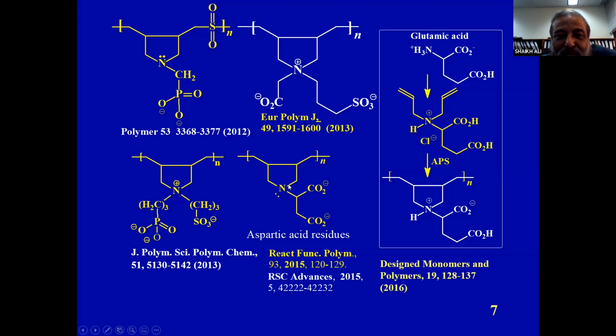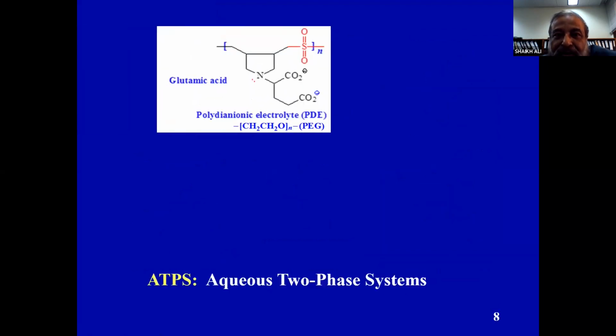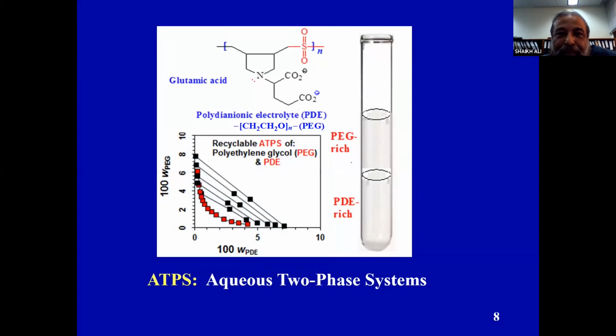And you can see here, this one has aspartic acid residues from the amino acid aspartic acid. And this one is from glutamic acid, and we got a polymer containing residues of glutamic acid. They are pH responsive. You can take this hydrogen, CO2 minus, CO2H, all these are pH responsive. Now, you see, if you take one of these systems, like this polymer we made, and we take polyethylene